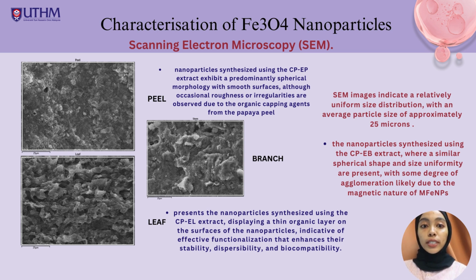The second sample, which is peel, nanoparticles synthesized using the CPEP extract exhibit a predominantly spherical morphology with a smooth surface. And the last sample, which is leaf, the nanoparticles synthesized using the CPEL extract display a thin organic layer on the surface of the nanoparticles, indicative of the effective functionalization that enhances their stability, dispersibility, and biocompatibility.